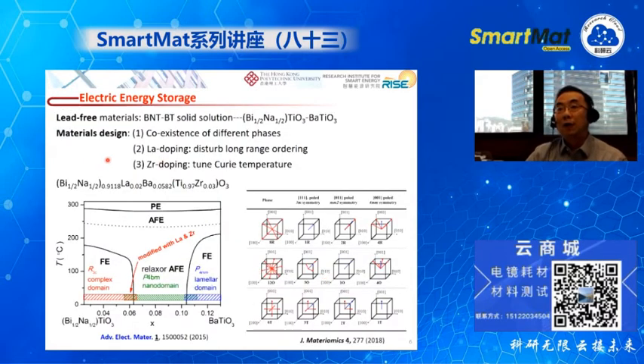So our first example is we make use of a lead-free perovskite material, which is a solid solution between BNT and BT. BNT is bismuth sodium titanate, and BT is barium titanate. It forms a solid solution, and this is the phase diagram for the BNT-BT. You can see the different compositions, right?